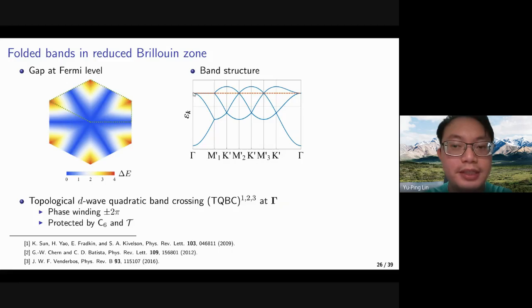An important point is that if we look at the gamma point, there are some positive energy and negative energy regimes around it. It is because the gamma point dispersion energies are inherited from the original cell's M point, so they are d-wave. And this kind of topological d-wave quadratic band crossing is non-trivial because it will have a 2-pi phase winding when we go around it. This is protected by both C6 and time reversal symmetries. So we will show that the density wave can gap out the quadratic band crossing and induce some topological nature.